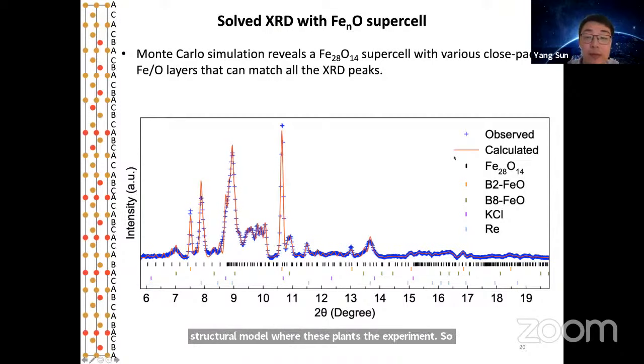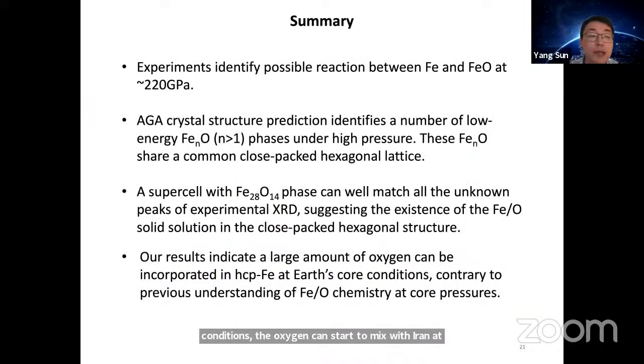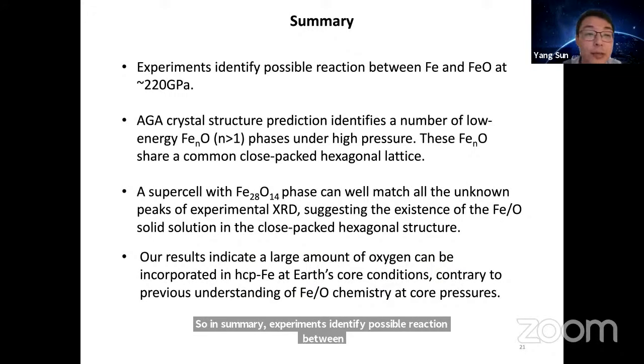So we believe it proves that at the laboratory condition, the oxygen can start to mix with iron at iron-rich site and forms this layered close-packed structure. So in summary, experiments identify possible reaction between iron and iron monoxide at 220 gigapascal.